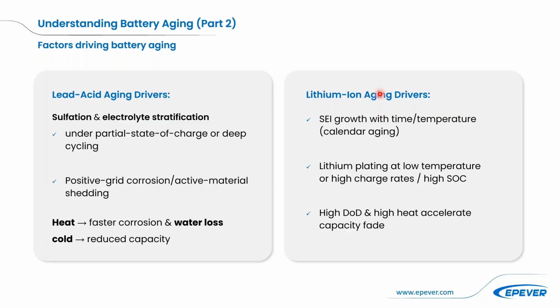So for lithium ion, it's slightly different. LiFePO4, basically in our context. Over time, the SEI layer thickens. Then we have classic calendar aging, driven by temperature and state of charge. And if you push hard charging in the cold or at high SOC, you risk lithium plating, and this steals cyclable lithium and raises impedance in your system. So deep cycling and high temperatures also guide the chemistry for lithium batteries along the wrong paths. So DOD and heat management really matter. Depth of discharge and temperature management are crucial for lithium battery aging.